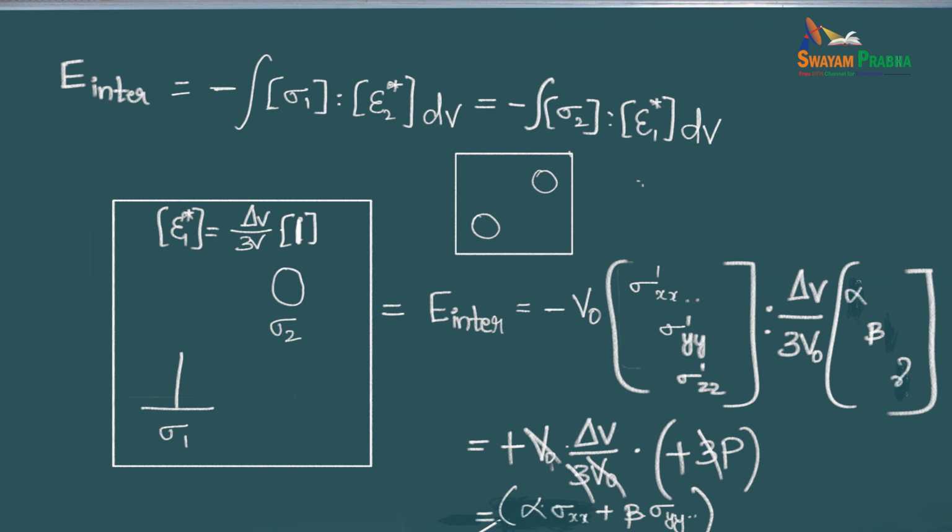So now the interaction of a shear is going to be the same as the P delta here. The interaction of a shear stress with another solute is zero. So actually, a field of centers of traction, of compression or dilatation, they do not interact with one another. They don't see each other. There's no interaction energy. And actually, you can push that result further.